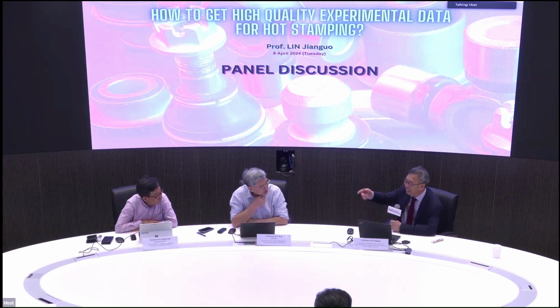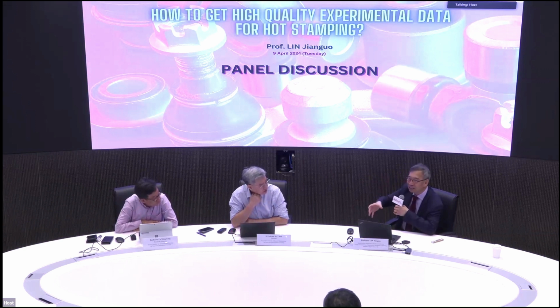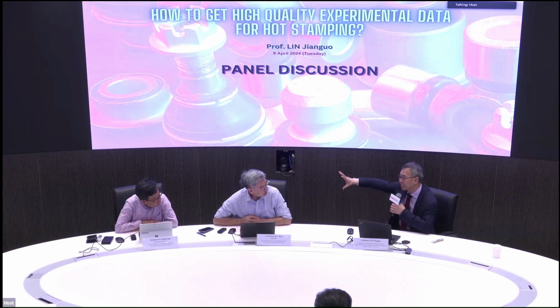For aluminium, slightly different mechanisms. That's a solution heat-treated material. We need to get a fully solution heat-treated state to enable the part to be formed. So you need a longer soaking time? Not so. Yes, if the C curves move to the right-hand side, that's better. But sometimes it's difficult.